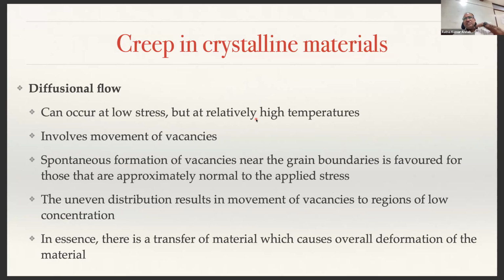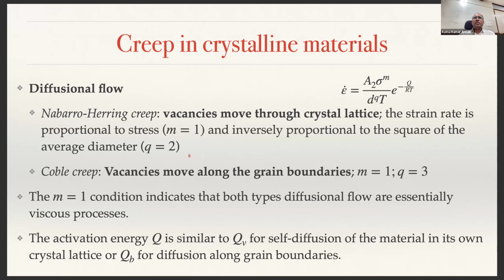As I said, there are three mechanisms. One is diffusional flow. This can take place at low stresses but very high temperatures, because at high temperature diffusion can take place. That means atomic motion can happen over long distances, which will create vacancies in the material. They will create spontaneous vacancy formation near grain boundaries, and even at a lower stress, that will cause some deformation. Diffusional creep is also represented by something called Nabarro-Herring creep.